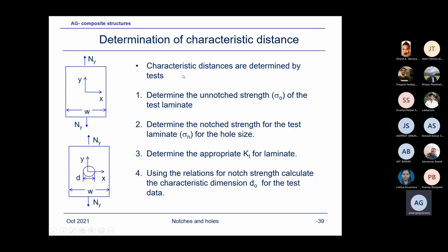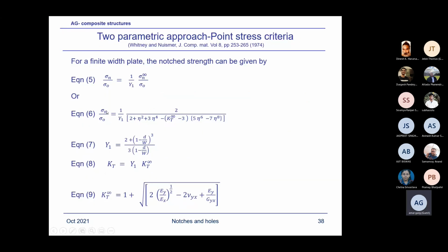So characteristic distances are determined by test. Determine the unnotched strength, sigma naught, of the test laminate by testing unnotched coupons. Determine the notch strength of the laminate for the hole size. So suppose this is a D diameter, test this coupon. Determine the appropriate KT for the laminate. Using the ratios for the notch strength, calculate the characteristic dimension d naught for the test data. So in this equation, if you know sigma n, you know sigma naught, the only unknown over here is eta, which is a function of d naught. So you can calculate d naught using this equation.